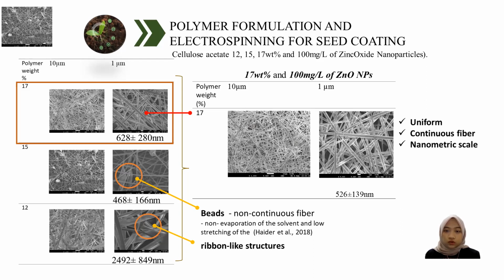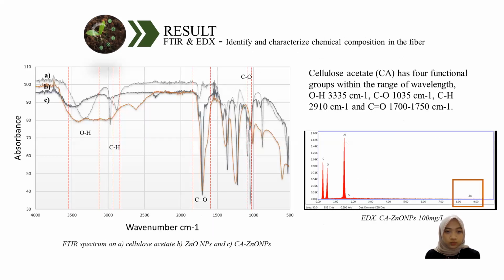With the inclusion of the zinc oxide nanoparticles, zinc oxide increases the conductivity level of the solution. Thus, we are able to produce finer fiber compared to cellulose acetate alone.